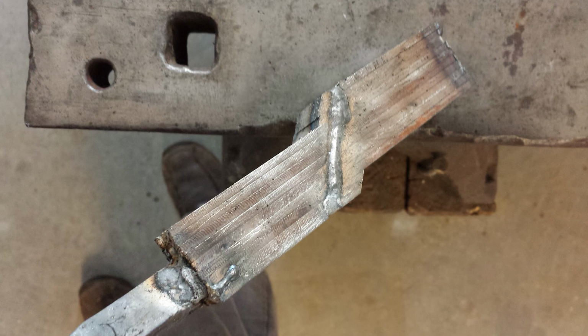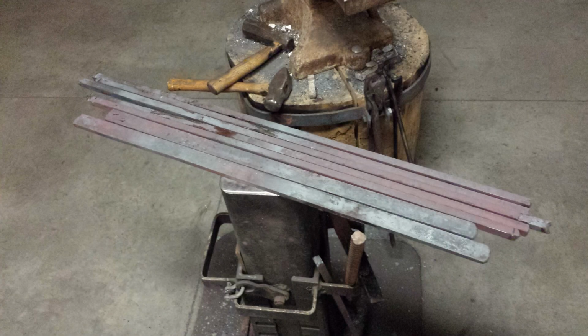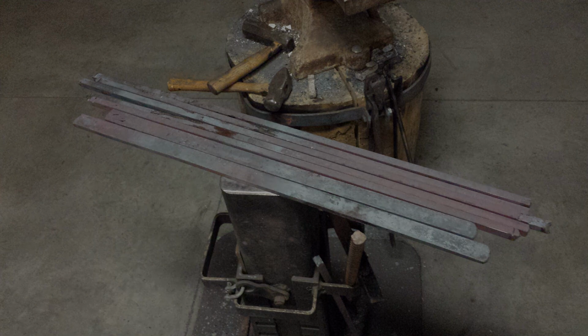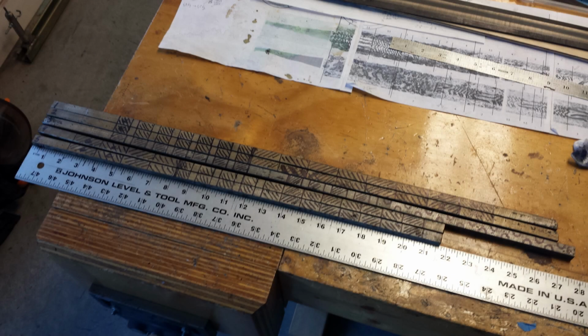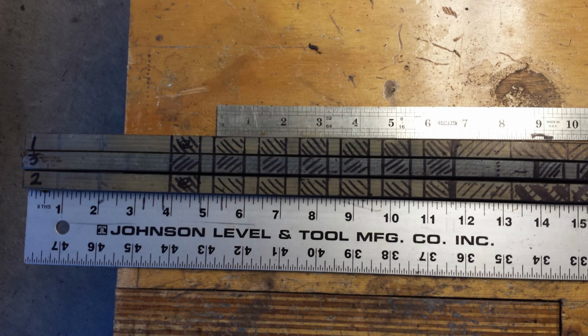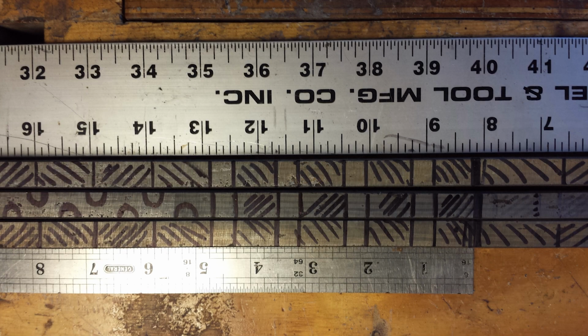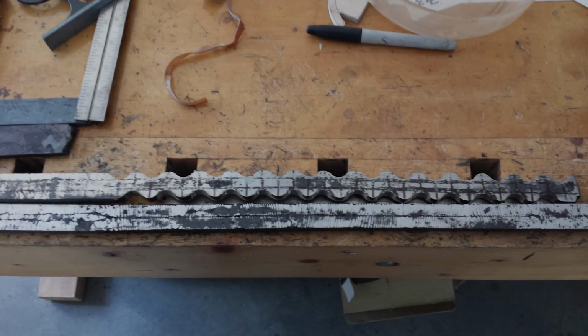By now you know the process. First make the billets, and while they are hot, turn it into bars. Clean up the bars, lay out the twists. This is the 3-bar chevron straight on the opposite side, the 2-bar checkers, the 3-bar chevron is straight on the serpent side. The serpent will be done by grinding, but this time I will make the waves tighter. Square the bars thinner than 3/8 of an inch to avoid having as much wasted metal.